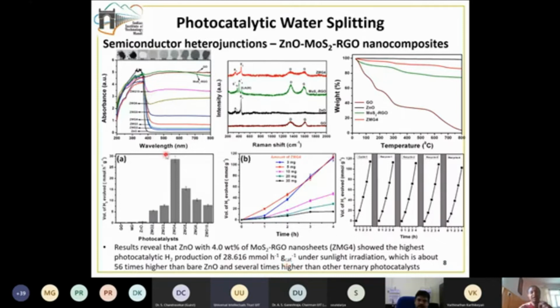Why is this particular ZMG4 sample giving the best result? That's a question, because we can see from this absorbance data that ZMG4 has good absorbance in visible light, but the other samples have even better absorbance in the visible light. So why are the other samples not giving a better result? Here we can see that this ZMG4 sample has an optimal amount of MoS2 and RGO along with zinc oxide. When we further increase the concentration of MoS2 and RGO, for example in ZMG5, 6, and 10, the sample becomes darker and darker. The active semiconductor is the zinc oxide, and it is covered by this dark colored MoS2 and RGO, which is not allowing the sunlight to interact with the energy levels of the zinc oxide. So that's the reason we could say that ZMG4 gives the best result here.